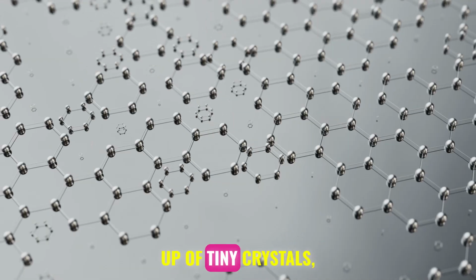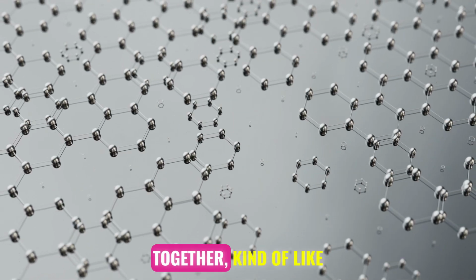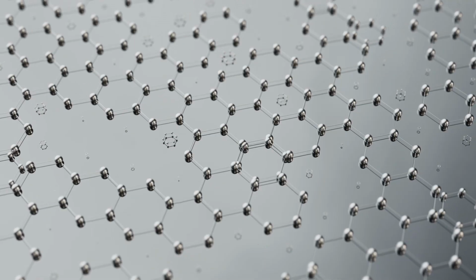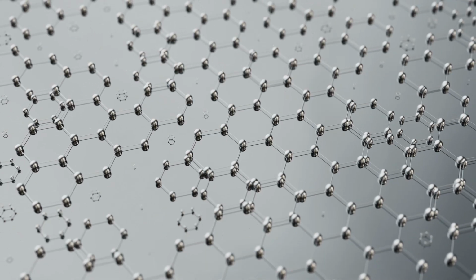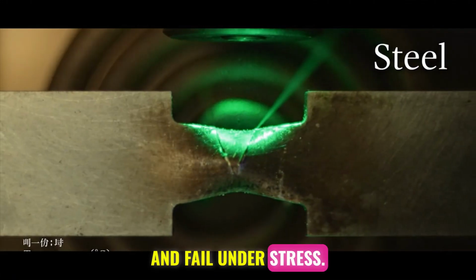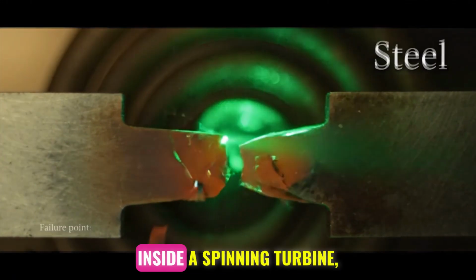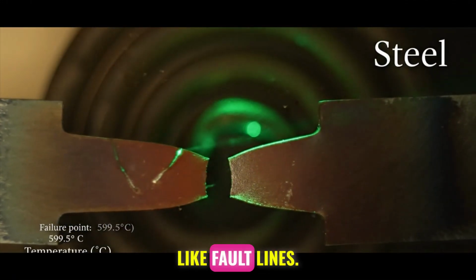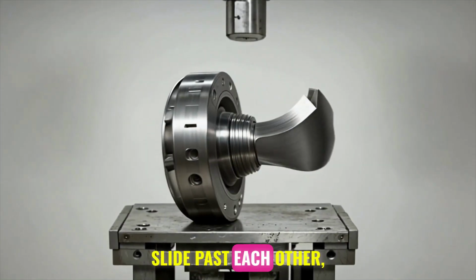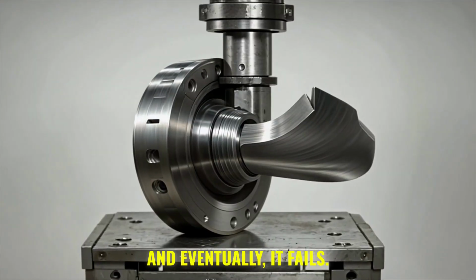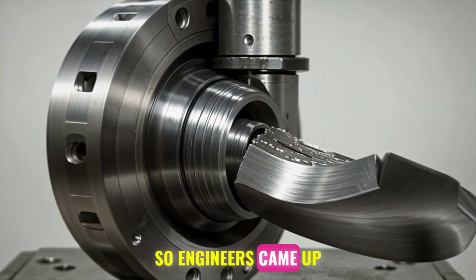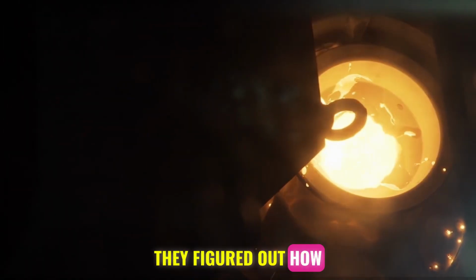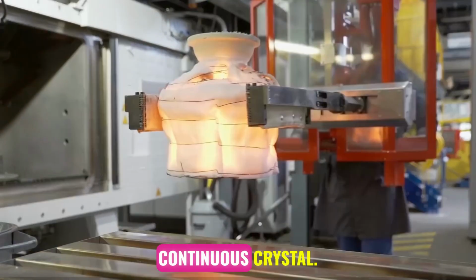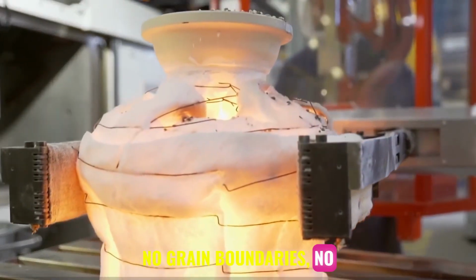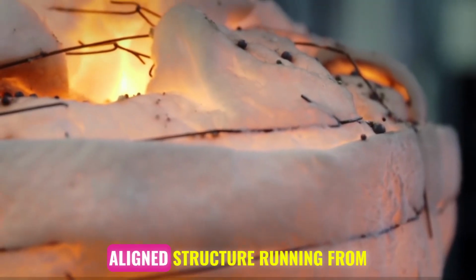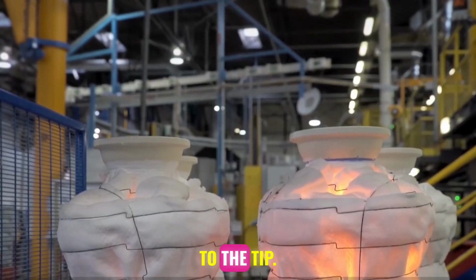All metals are made up of tiny crystals, millions of them packed together, kind of like grains inside a sugar cube. And the boundaries where those crystals meet? That's where metals crack and fail under stress. Under the extreme forces inside a spinning turbine, those grain boundaries are like fault lines. The crystals start to slide past each other, the blade slowly deforms, and eventually, it fails. So engineers came up with something remarkable. They figured out how to grow each turbine blade as a single continuous crystal. No grain boundaries, no fault lines. One perfectly aligned structure running from the base of the blade all the way to the tip.